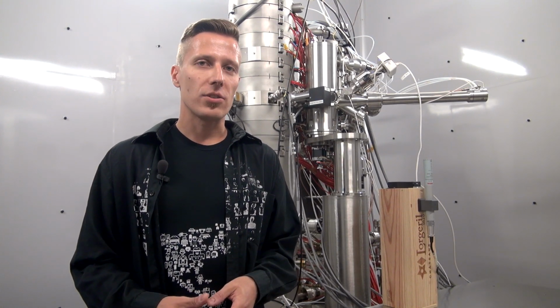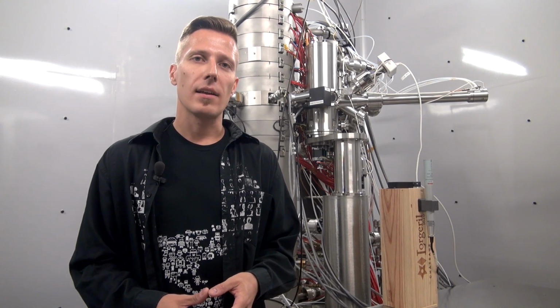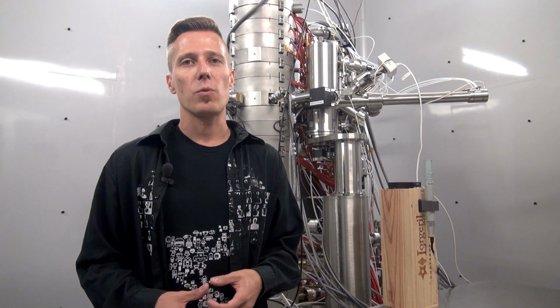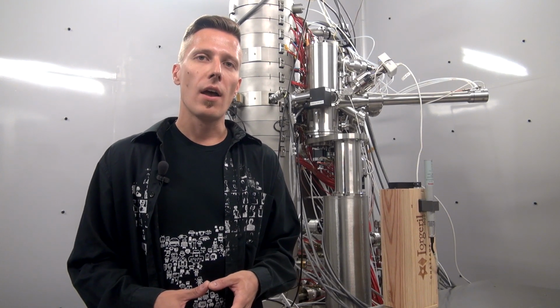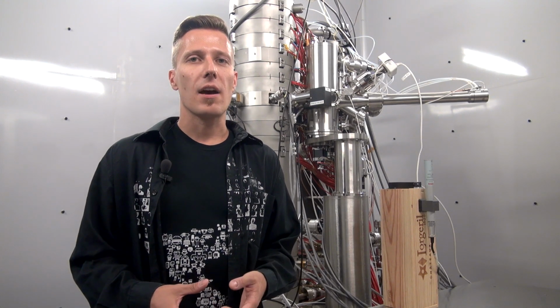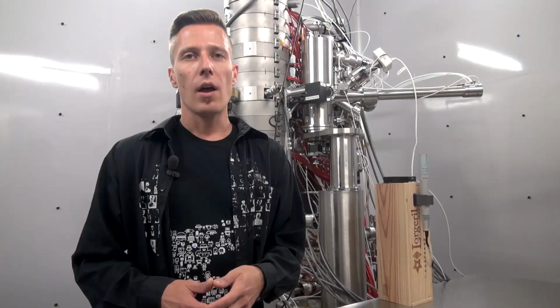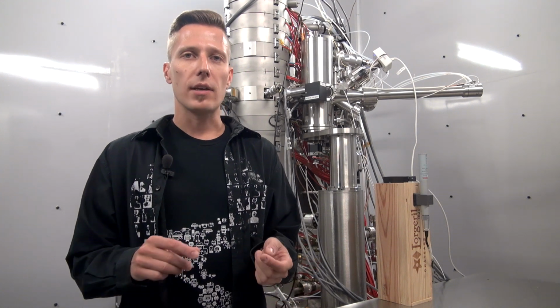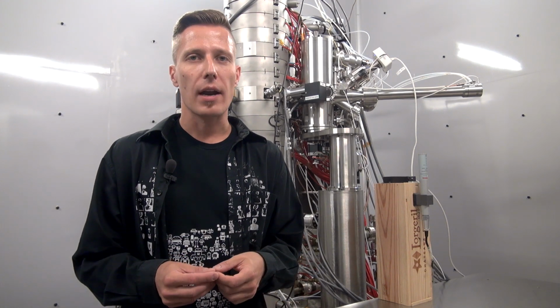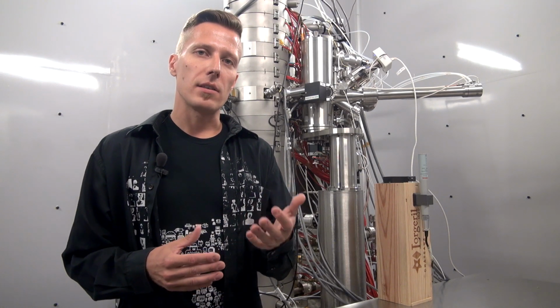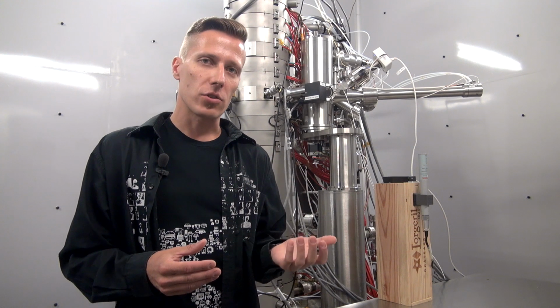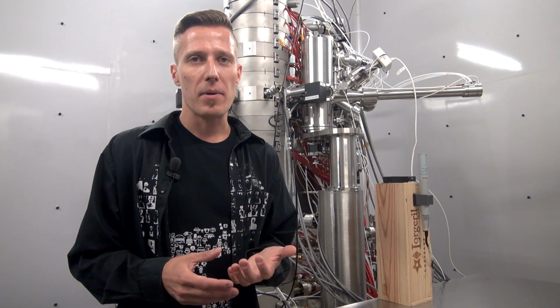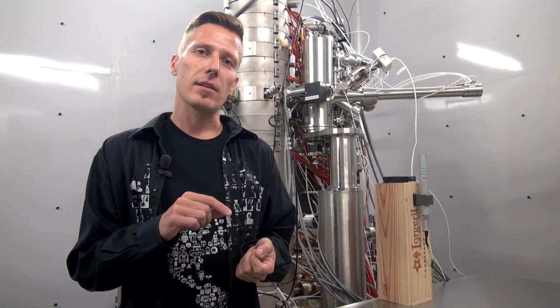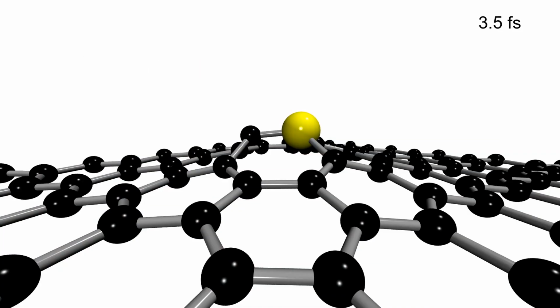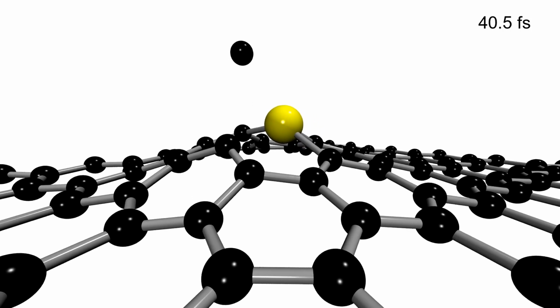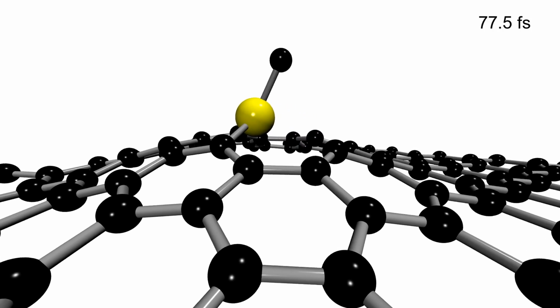The detailed and computationally demanding simulations told us that at an acceleration voltage of 60 kilovolts, which the cutting-edge electron microscopes use, the probe electrons are not energetic enough to cause direct knock-on damage. Crucially, the carbon atoms next to the silicon dopant are slightly less strongly bound than other atoms in the structure. So while the 60 kilovolt electron beam is not enough to cause direct knock-on damage, it can impart enough of a kick to the carbon atoms next to the dopant so they fly up from the structure but get immediately recaptured due to the attractive interaction between the silicon and the carbon atom.